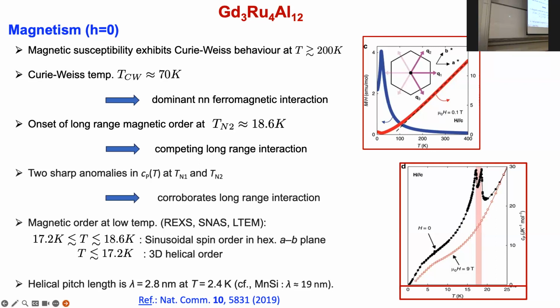Now at zero applied magnetic field, this is what the behavior looks like. The magnetic susceptibility exhibits Curie-Weiss behavior at higher temperatures. The Curie-Weiss temperature deduced from the high temperature behavior is about 70 Kelvin, which points towards a dominant ferromagnetic exchange. But you do not observe any long-range magnetic order all the way down to 18.6 Kelvin, which indicates that there must be some competing interactions preventing the onset of magnetic order at higher temperatures.